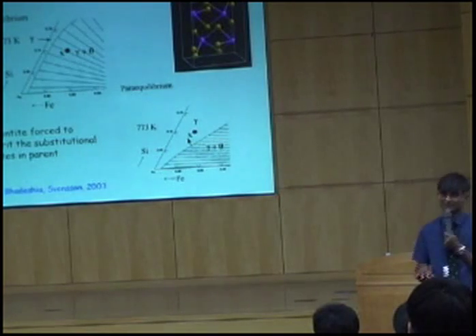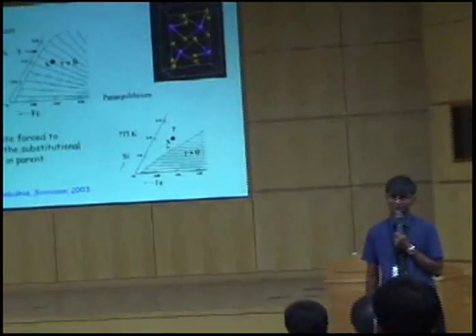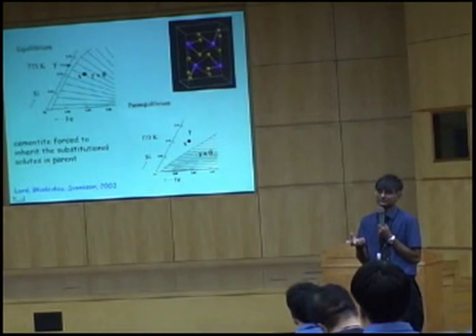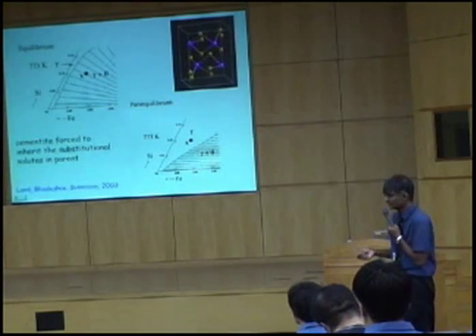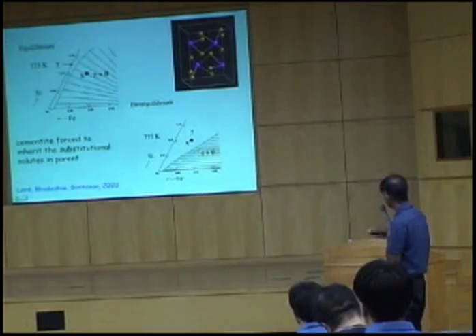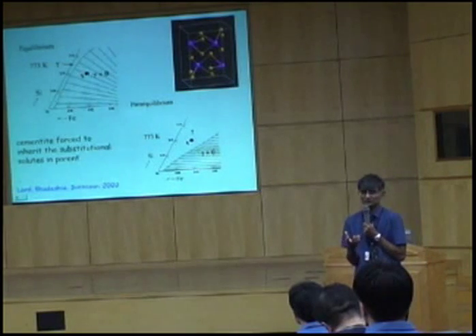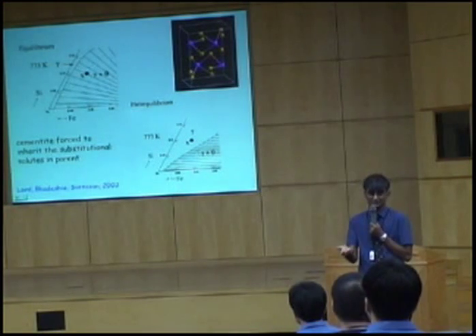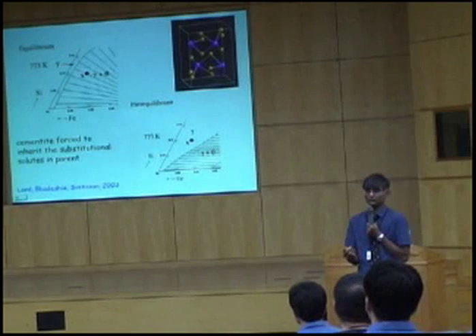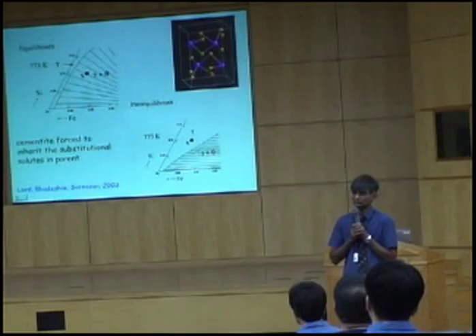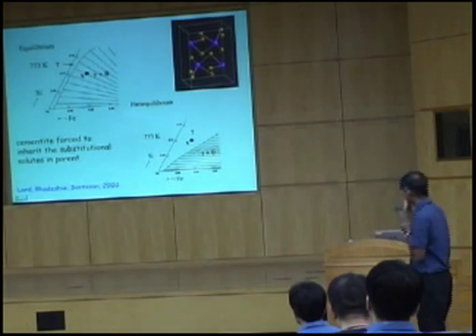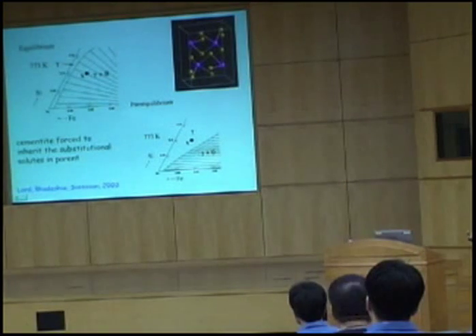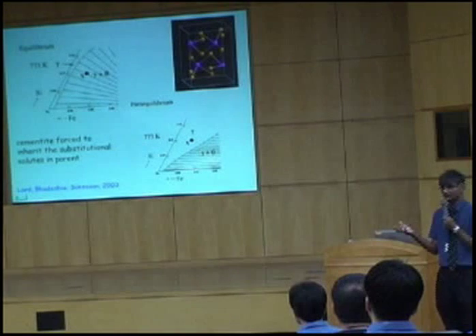So if you do not allow the silicon to partition, then the cementite will not form, because it hates silicon so much. Okay? So the mechanism by which silicon and aluminum prevent the precipitation of cementite is simple. If you form the cementite at a low temperature, it is forced to accept the silicon, which it does not like, and therefore it will prefer not to form. Okay? So this method of preventing cementite formation has been known for more than 100 years.